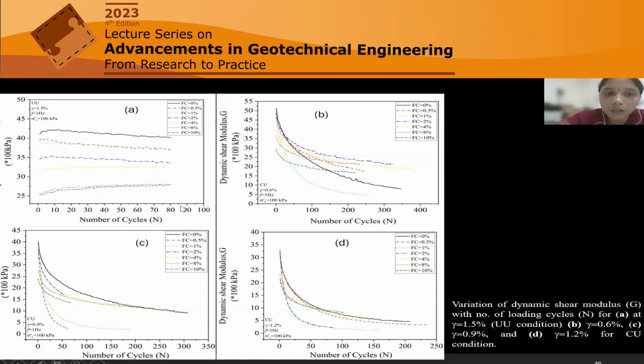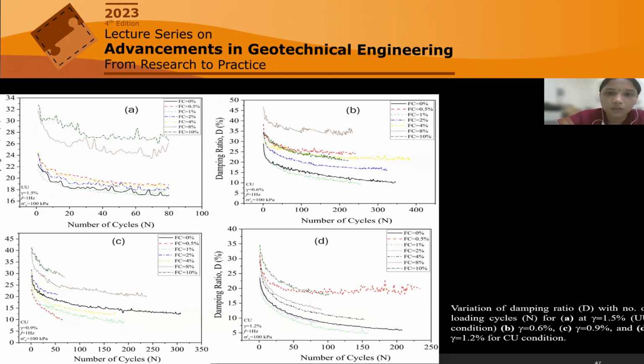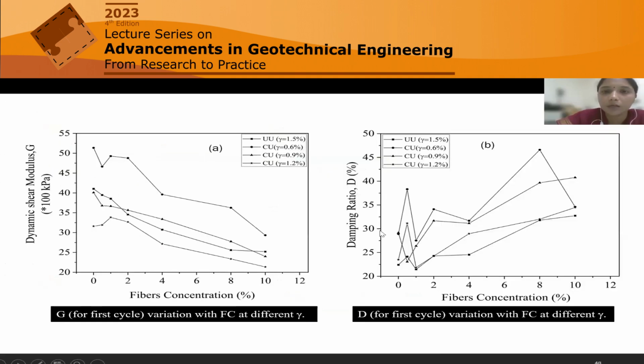In the figure, A is the UU result, and B, C, D are CU results. For the CU case, we get a decrease in G value with increase in number of cycles, but for UU we do not get that. This is because the sample is not even saturated; it is only a compacted sample, and we applied dynamic loading. And this shows the damping ratio variation with number of cycles for the different reinforcement cases. This is the summary of our second part, the dynamic test results: dynamic shear modulus and damping ratio variation with fiber concentration from 0 to 10%.